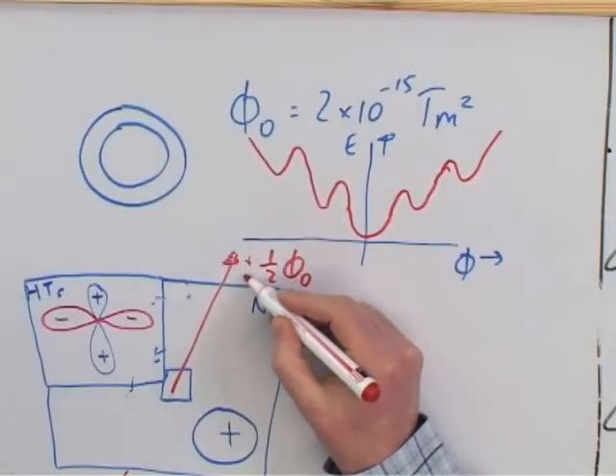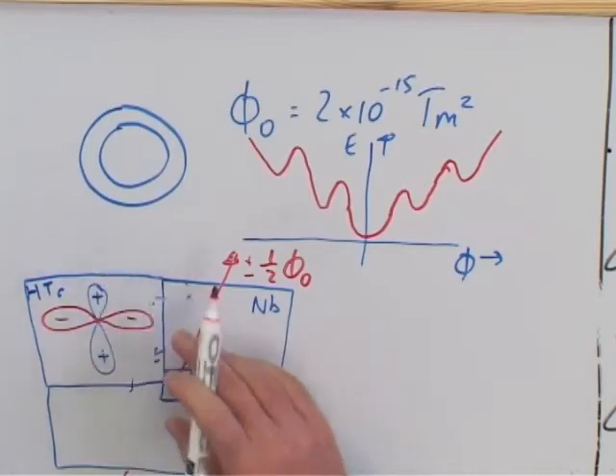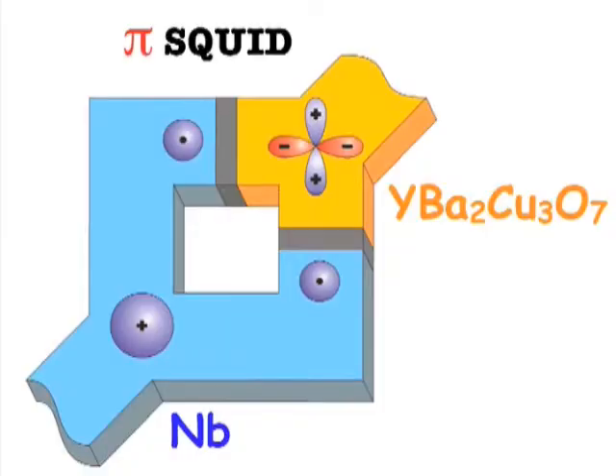Another very interesting aspect is that the sign of this half flux quantum doesn't matter — it can be either plus or minus. So there are two possibilities: you have a half flux quantum sticking out of the board, or going into the board. I find this very fascinating, because you have a connection of two materials, a high-temperature superconductor and a low-temperature superconductor, which both are non-magnetic. You don't apply any currents, you don't apply any magnetic fields. You just connect them and cool them down below the transition temperature of both superconductors, and then spontaneously you get this generation of a half magnetic flux quantum.